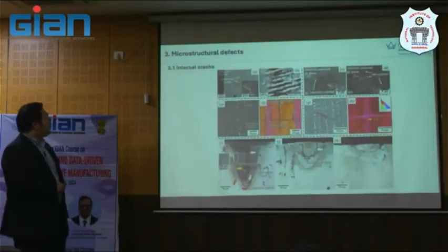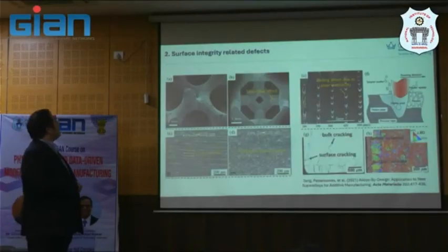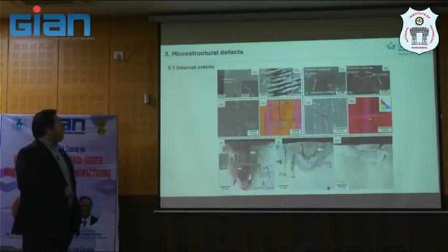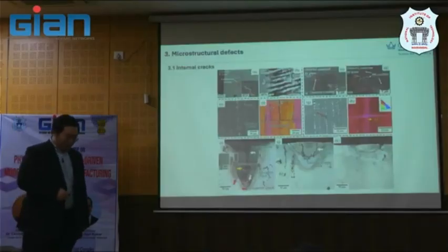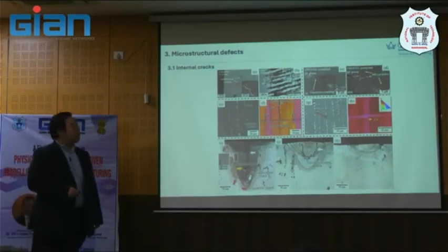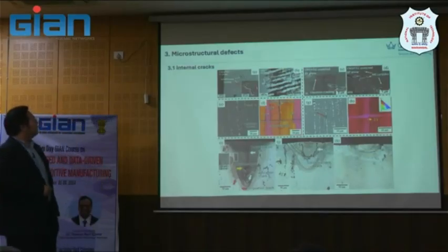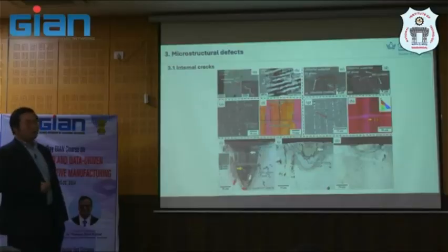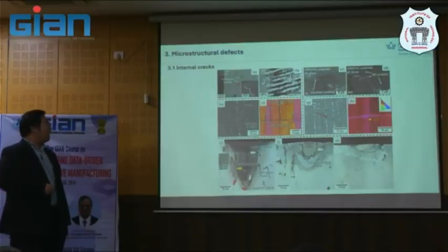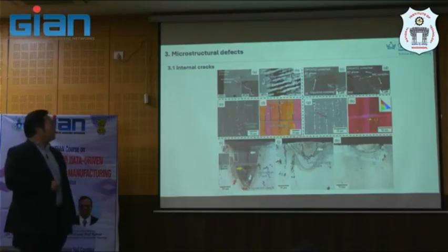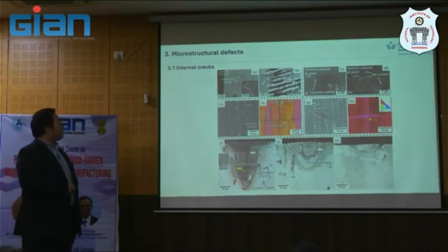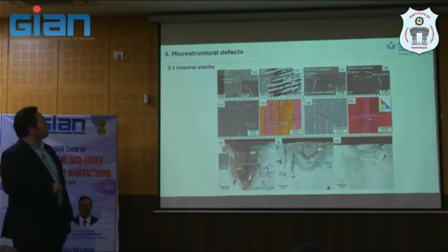So in terms of microstructure defect, there are so many microstructures that link to composition, link to the processing as well. But again, this is the internal crack. So basically, this is a solid mechanics kind of effect that you see, solidification cracking. Why do we say solidification cracking? Because it's evident from the small dendrite.